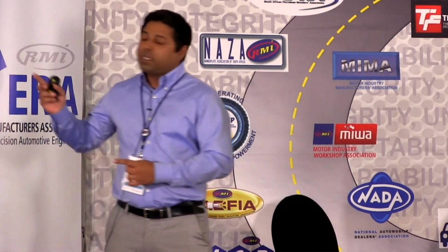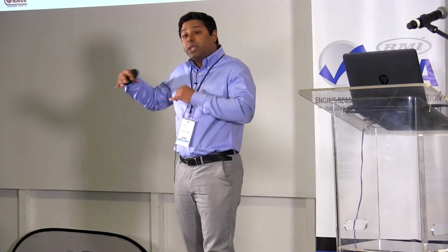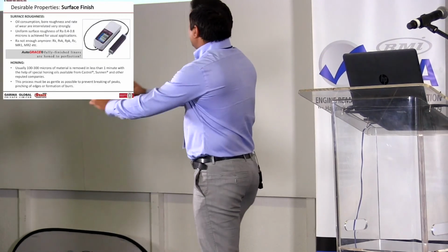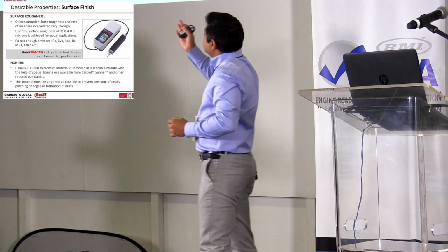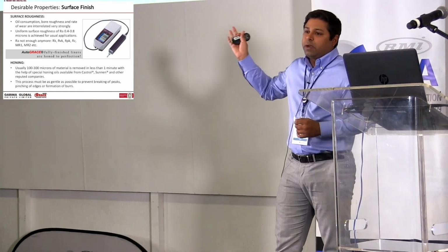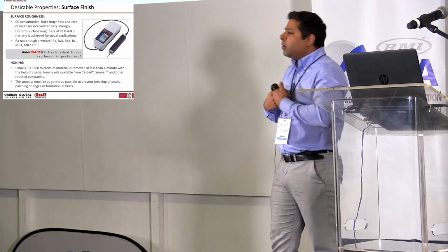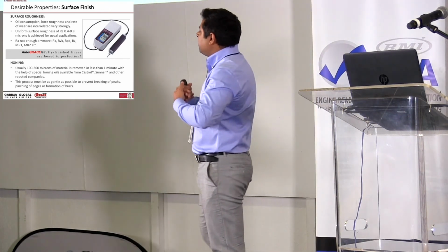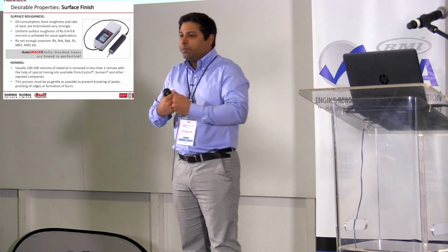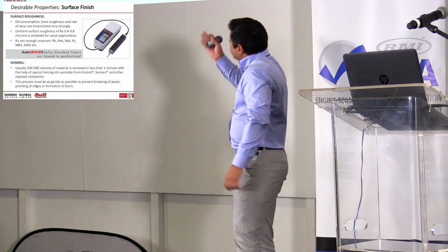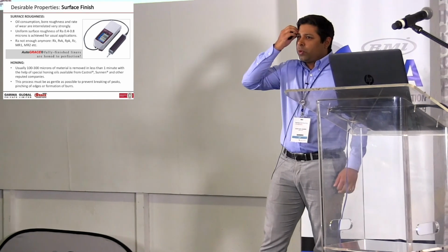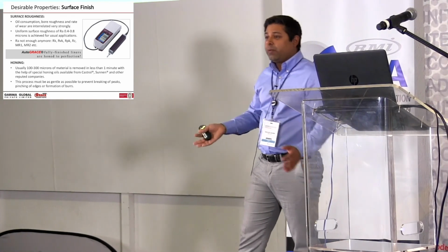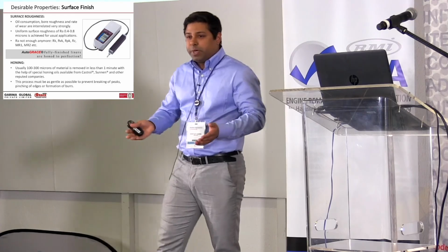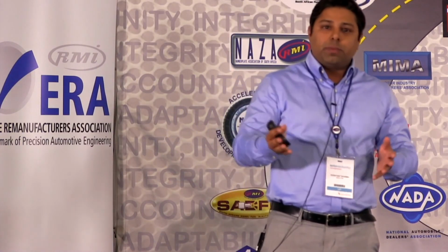Surface finish, as I mentioned before, of the inside as well as the outside diameter is critical for a good liner. Now, oil consumption, bore roughness, and the rate at which the liner wears out are all very tightly related factors, and they all affect engine performance. About 20 odd years ago, RA was the primary measurement that would tell you something about the surface finish. But today, RA is not enough.